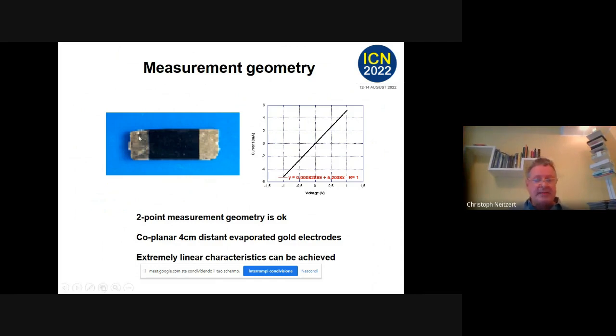If you do this, you have here a perfect linear resistor, if you don't exceed too much the voltage, otherwise you have self-heating and it becomes a little bit nonlinear. You see the correlation is 1, it's perfect. It's a linear resistor. You see we have about 5 milliampere at 1 volt. So that means 200 ohm.